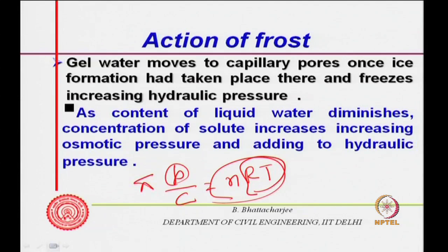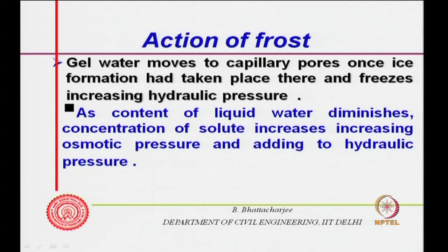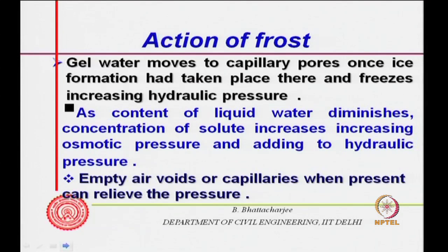So, the osmotic pressure can be related to the gas law and so on and so forth. So, that is what it is. The solute concentration being different can cause an osmotic pressure and it can add to the hydraulic pressure. Empty air voids or capillaries, when present, can relieve this pressure. Supposing I have empty capillaries or empty voids which are not filled with water, when hydrostatic pressure is applied, this gets ruptured and the water can enter into this one and this can relieve some of this pressure.